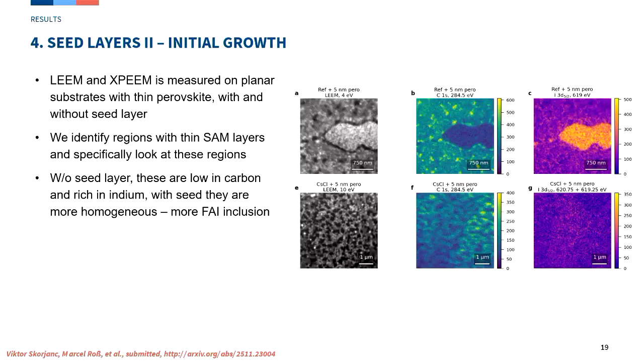We do elemental mapping to understand how the perovskite grows and why the seed layer improves growth. Coming back to our SAM layers, what we see is bright spots, very dark ones, and grayish spots. That is our self-assembled monolayers forming various different heights at the surface. You see a very thick layer here, a medium one, and a thinner layer. That also leads to different growth of the perovskite on top. So it's very sensitive to what is underneath. You see the carbon signal changing, and we also have indium signals showing that the ITO, the transparent electrode underneath, is showing through in those regions.